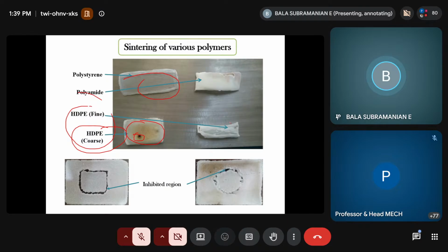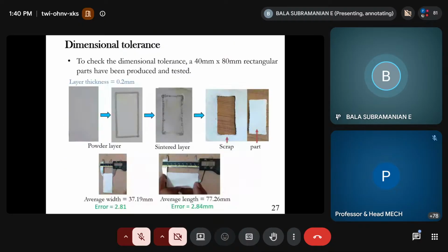That is what I said, the dispersion, how much it is being dispersed in this region. Okay, so this is the dispersion which was due to the isopropyl alcohol, control of isopropyl alcohol. So the inhibitor, how much it is being dispersed. So this is the simple measurement after sintering and inhibition.